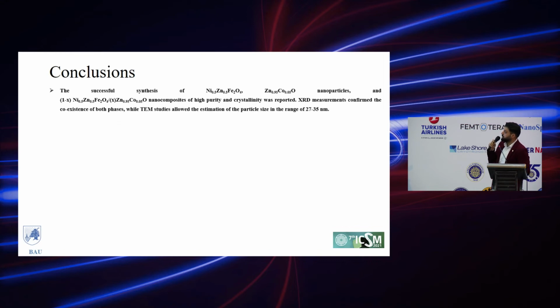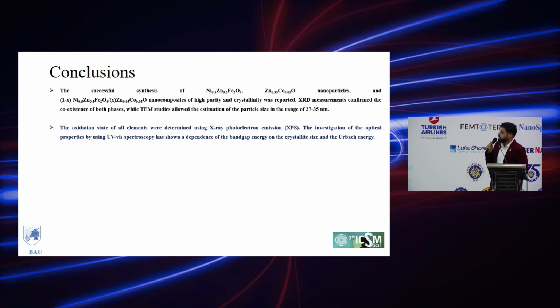Conclusions. So, successful synthesis of both nanoparticles and nanocomposites was reported, and the grain size was found in the range of 27 to 35 nanometers. The oxidation states of all elements were determined by using XPS studies. Optical properties investigated using ultraviolet-visible spectroscopy have shown the dependence of the bandgap energy on both the crystallite size and the Urbach energy.